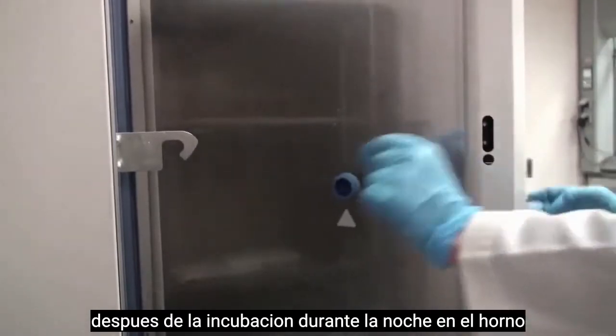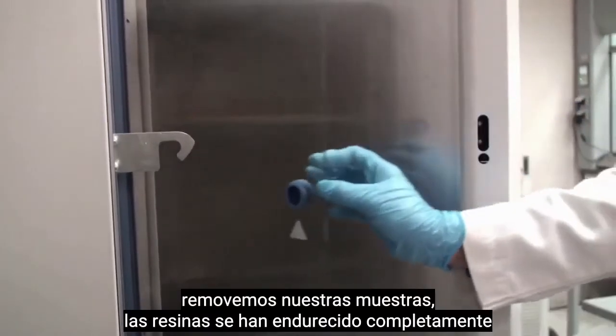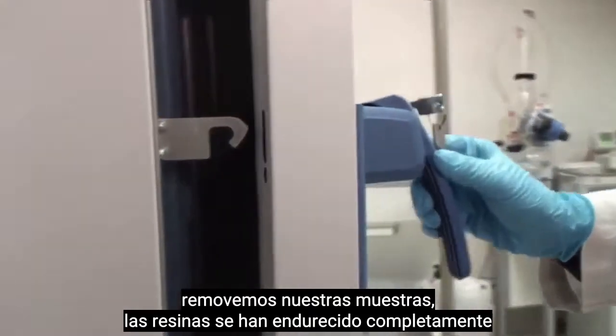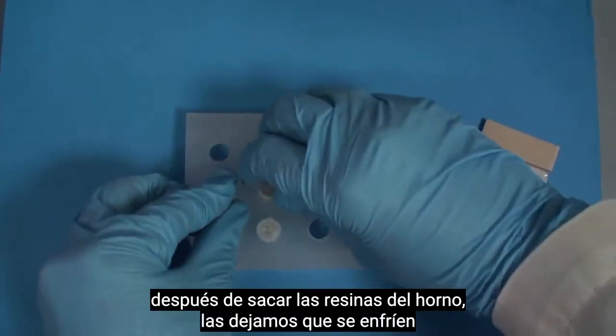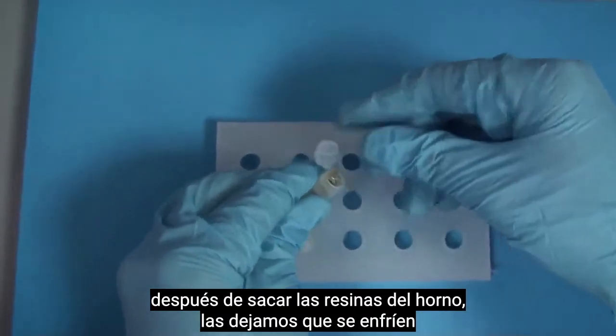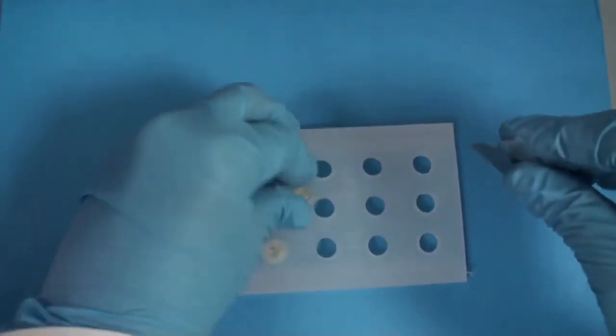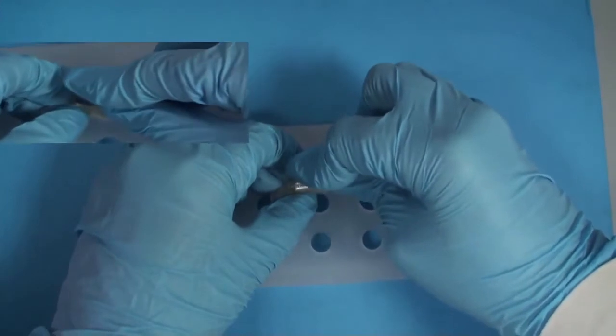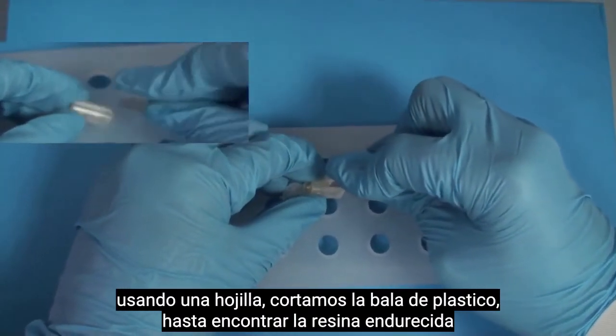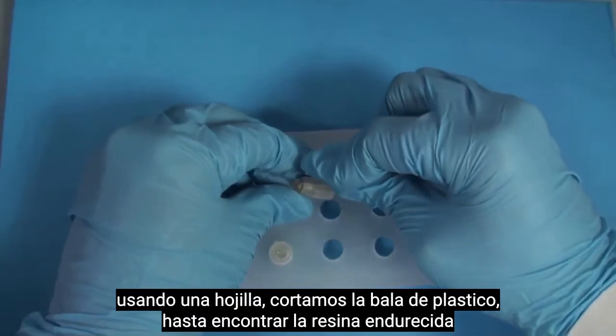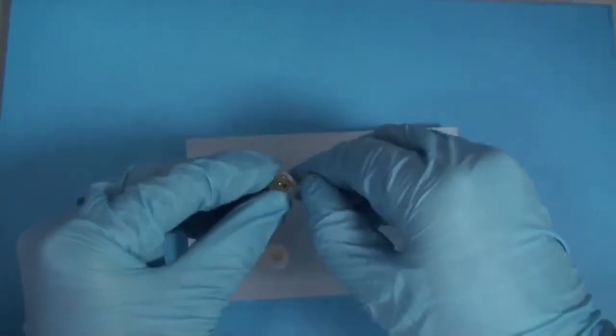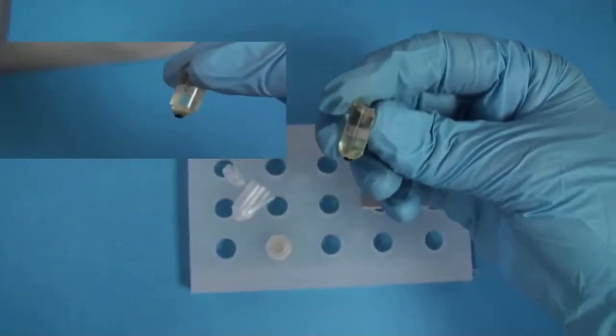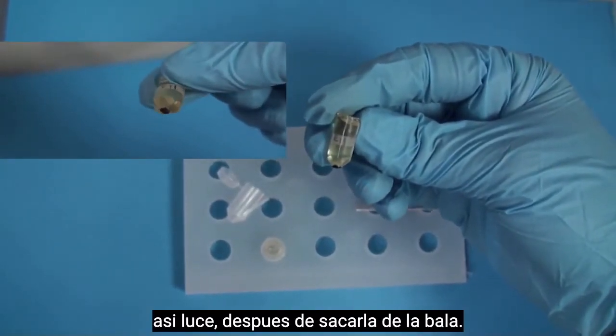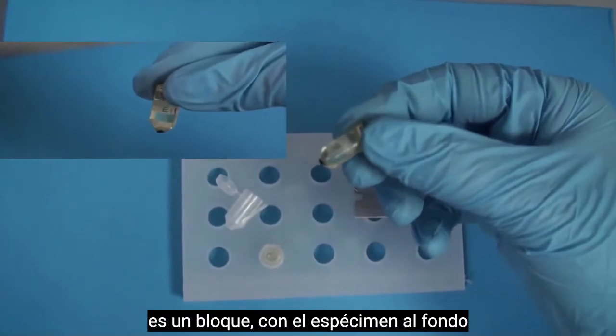After the overnight incubation in the oven, we will remove our sample where the resin has completely hardened. After the bullet was removed from the oven, we leave it for some time so that it comes down to room temperature. And then, using a blade, we cut off the plastic bullet to reach the hardened resin. This is how it will look like after we remove it from the bullet. It's a block with the specimen at the bottom of it.